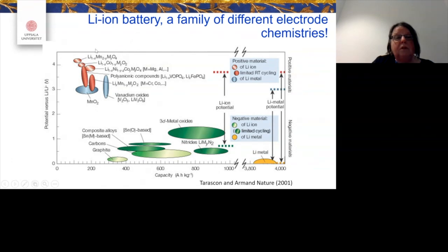But if you look at the positive electrode materials, you see that they have lower gravimetric capacity than graphite, so graphite is still doing fine. The holy grail is really to press the positive electrode to higher capacities. You can do that either by trying to shift the amount of lithium you can host in the atomic structure, or press the potential up to higher potentials.